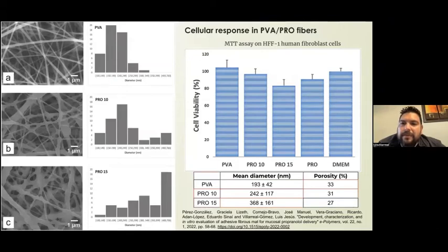If you use a lower molecular weight, you can improve the degradation rate of these fibers, and it is intended to release propranolol, the propranolol drug. In this case, we also tested with human fibroblast cells, and as you can see, not much alteration in the cell viability can be observed with the fibers. These 10 and 15 are the percentages of propranolol loaded into the PVA fibers.